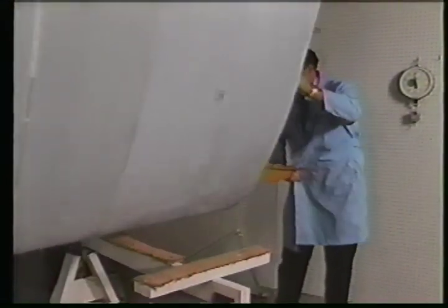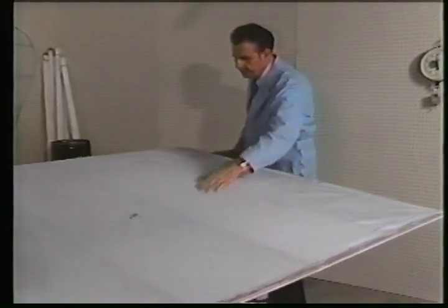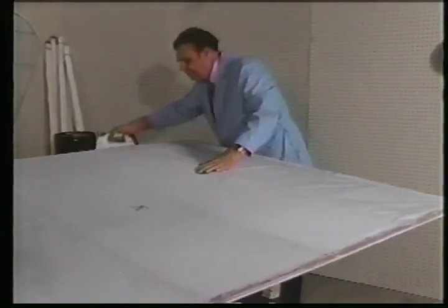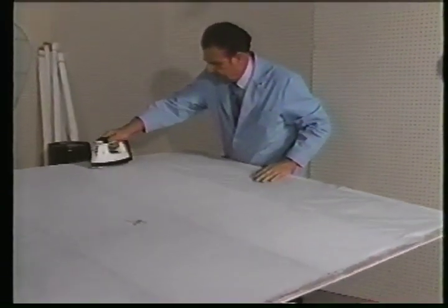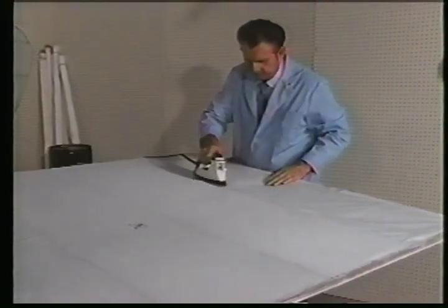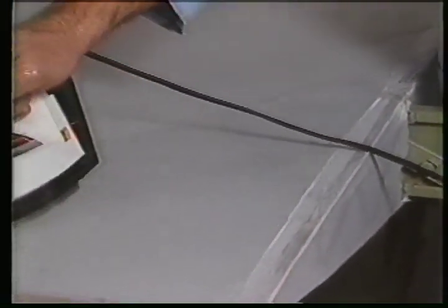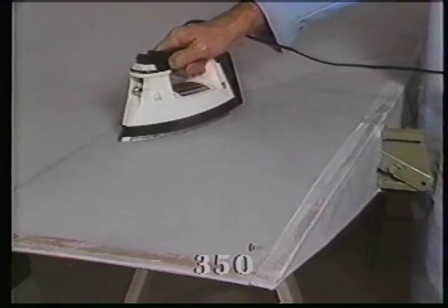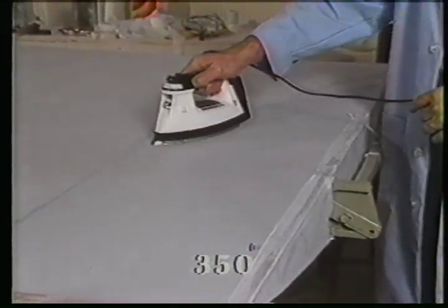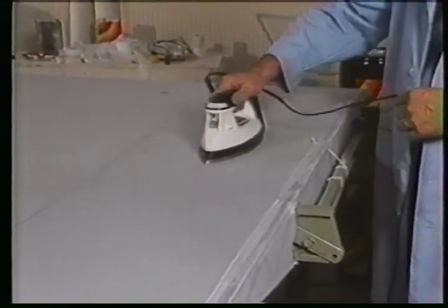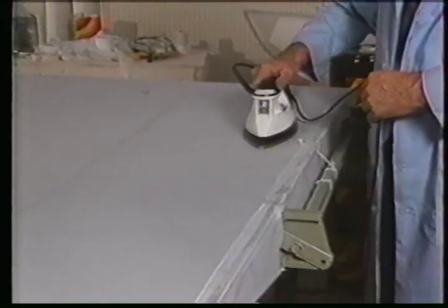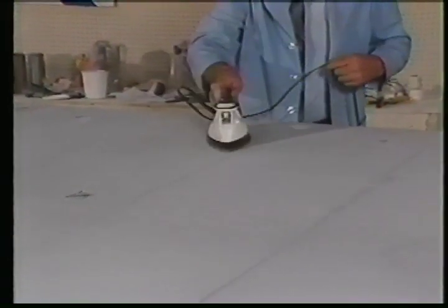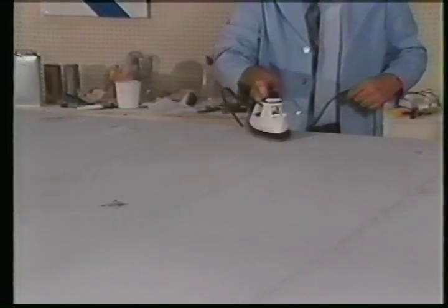After all the wrinkles are removed on one side of the wing, it is turned over and the other side taughted at 250 degrees in the same manner. After all areas on both sides have been heat taughted and wrinkles removed at 250 degrees, the temperature is increased to 350 degrees, and again, moved in contact over all areas at 4 to 7 inches per second. The two-step shrinking technique is intended to avoid distortion of the fabric weave pattern and any seams when all the shrinking takes place in a few areas.